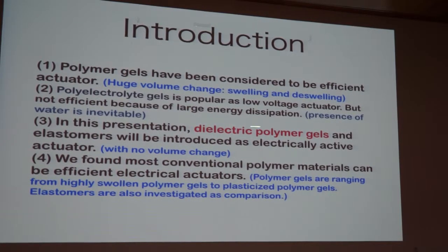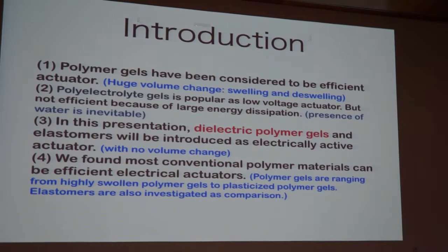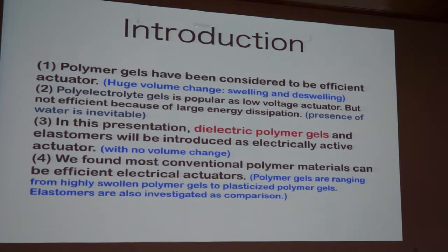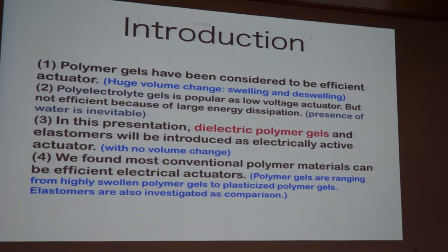But at that point, people advised me it's not adequate because dielectric materials cannot respond to a DC electric field. But I tried, and it turned out to be very active, and a huge deformation can be induced in this case. That's the starting point where I got involved with dielectric polymer gels. No volume change is necessary, and durability is much higher than hydrogels. After this, we found most conventional polymers can be applied for electrical actuators. For instance, polyethylene terephthalate, nylon, and many other polymers can be used as electrically active polymer actuators.